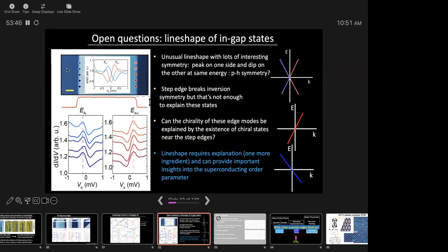It was much simpler than that. The idea is that as you have an STM tip at the step edge, although there's no conservation of momentum, the electrons that are going in come in with some preferential momentum, and that preferentially selects these or these. That's a very hand-waving explanation, but I could not think of any other way to get this kind of line shape. Similar argument, not exactly. We can talk about that later.